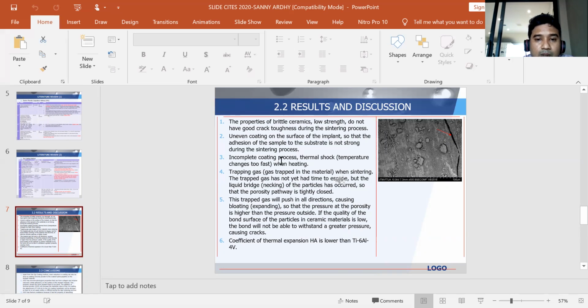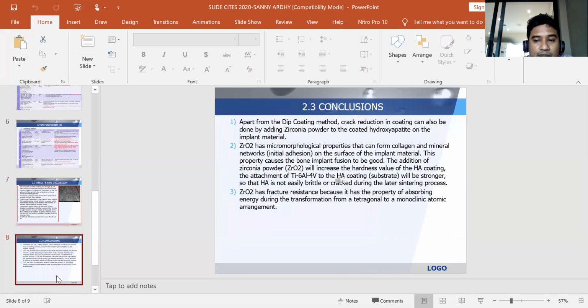Incomplete coating process, thermal shock, temperature change too fast when heating. Trapping gas when sintering. The trapped gas has not yet had time to escape, but the liquid bridge of the particle has occurred so that the porosity pathway is tightly closed.